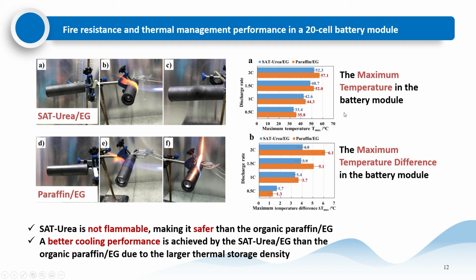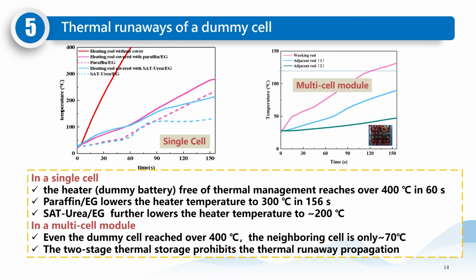We also use the PCM to cool down the battery when it operates normally. We can see that the battery temperature can be controlled within 52.3 degrees C, with the maximum temperature difference less than 4.0 degrees C. So it's a good material to cool down the battery.